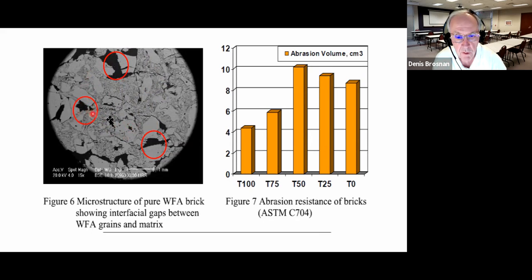best job in the world of filling this microstructure around these fused alumina particles. It's not easy to do, and there are a lot of cracks in this microstructure. In one case, the fused alumina particles were superior, and that was in abrasion resistance. And of course, fused alumina is a very, very high hardness material, and maybe you would expect that.